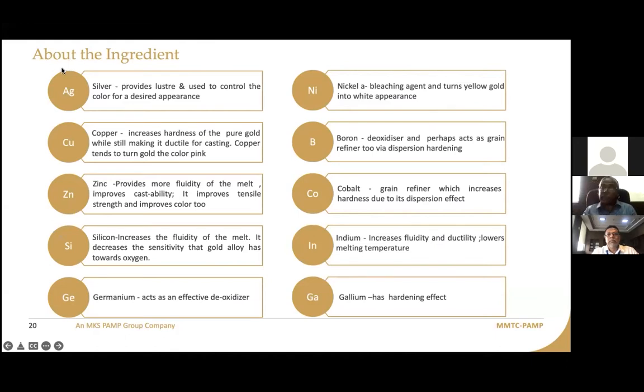But basically, nickel is a bleacher. Boron is a mild deoxidizer which can be added. It's a little reactive, very difficult to get dissolved, but it has its effect. At the same time, perhaps it also has some grain refining effect through dispersion hardening, as we call it metallurgically. So boron is also used in small quantities to act as a deoxidizer as well as a grain refiner.